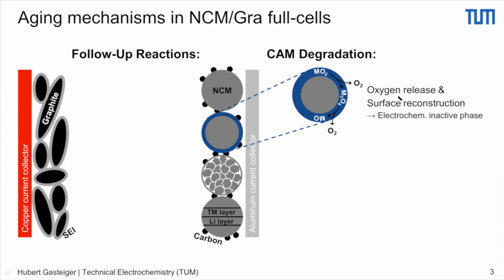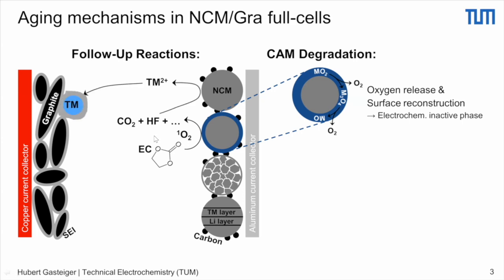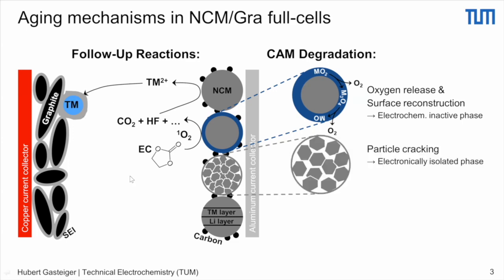We have a surface reconstruction, and we create an electrochemically inactive phase. In addition, during this oxygen release, we oxidize the electrolyte. Our hypothesis was that it goes via singlet oxygen, but there are of course other hypotheses in the literature. Nevertheless, what happens there is that you produce acidic species, typically HF, which leads to transition metal dissolution and migration to the anode.